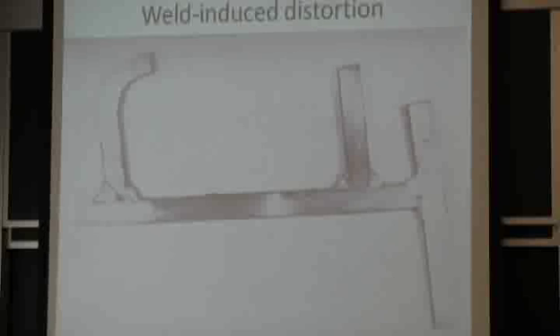Now, it's just an illustration. You have the same here with the end plate. The end plate is bent with the top to your left because they did this bigger weld here with a preparation right here. So it was cut at an angle to do the preparation. Now, if you are in a rig that will prevent that distortion, you know what you're getting, right? You're getting all these residual stresses, and you'll yield the metal, which a lot of the time is fine. I want you to be aware of everything that's happening, and that I thought was a good example.